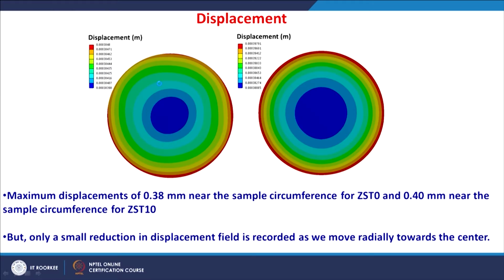We can also see the displacement analysis. Again, this is for ZS T0, this is ZS T10. A maximum displacement of around 0.38 mm near the sample circumference for ZS T0 and nearer 0.40 mm near the sample circumference of ZS T10 are found. You can see this is in meters. But only a small reduction in the displacement field is recorded as we move radially towards the center.